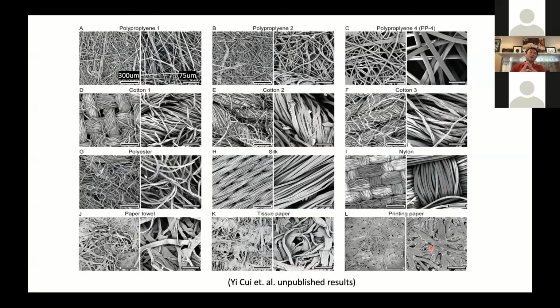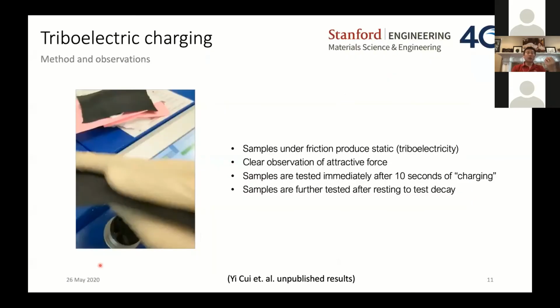So we can at the end come back to correlate. Number 1, if you want to learn what causes this, number 1 is microstructure. How does fiber arrange? You want to have those micron size, 10 micron size pores, but not 100 micron. Basically, that's the conclusion. And then to increase the filtration efficiency further, once you have the right microstructure, you need to have static charge in there. It really motivates us to look into whether we can generate a static charge in all these materials to really increase the filtration efficiency.